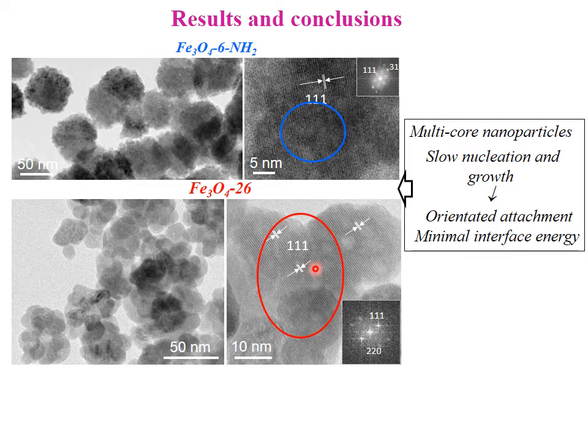In the magnetite 6NH2 sample, the concentration of OH groups on the surface of the particle should be low, since the water present in the reaction medium only comes from the hydration of the precursor. Therefore, the growth of the particle must be slow.